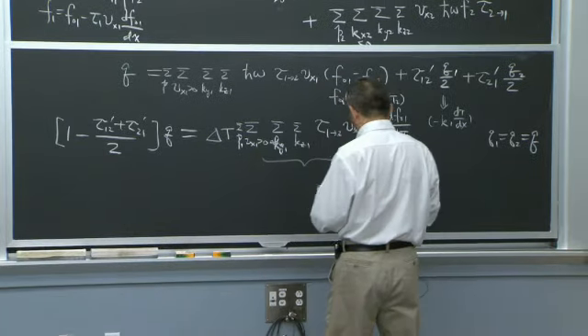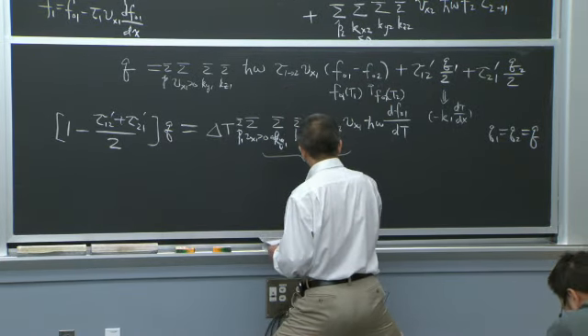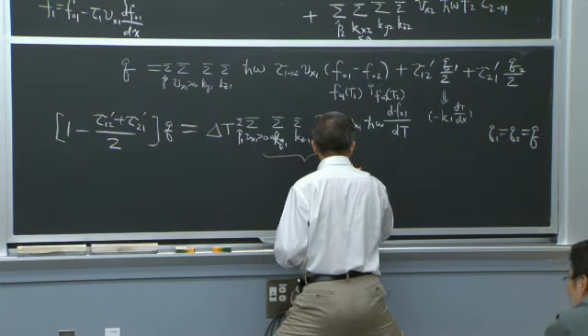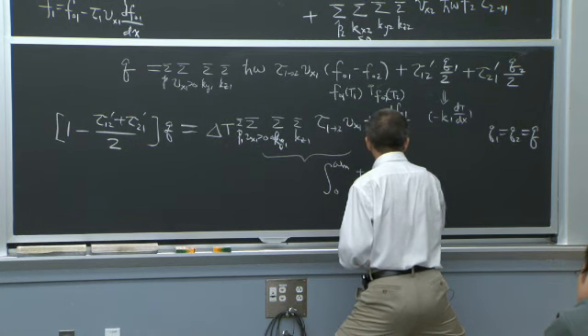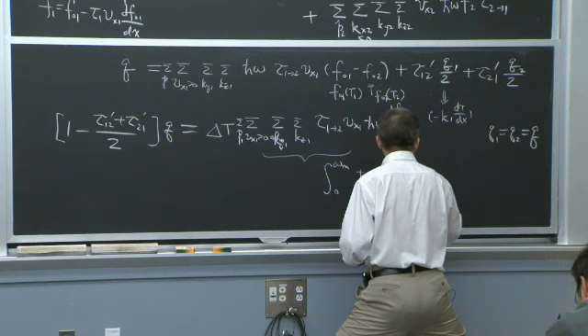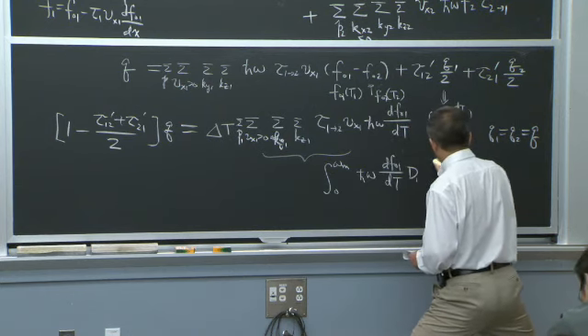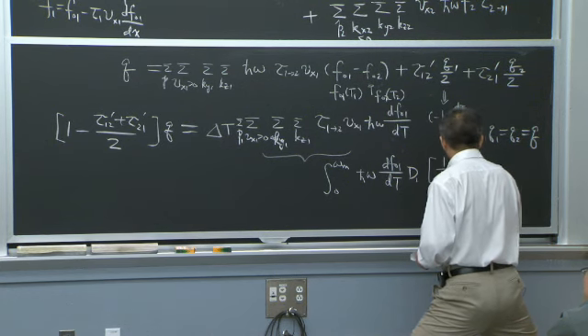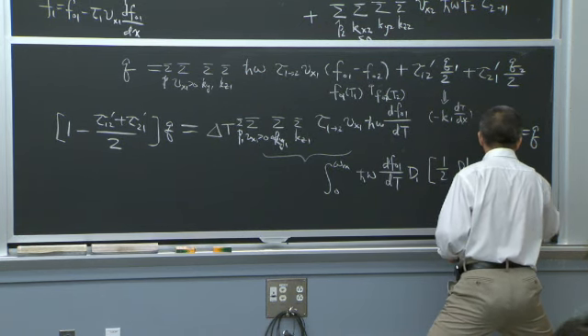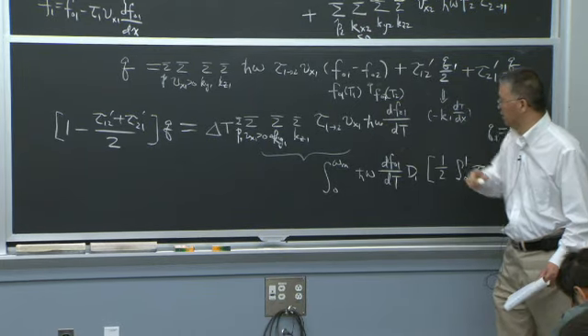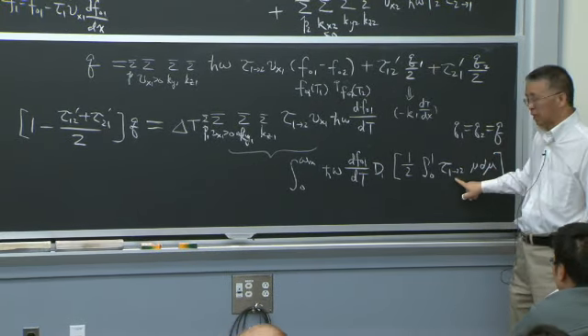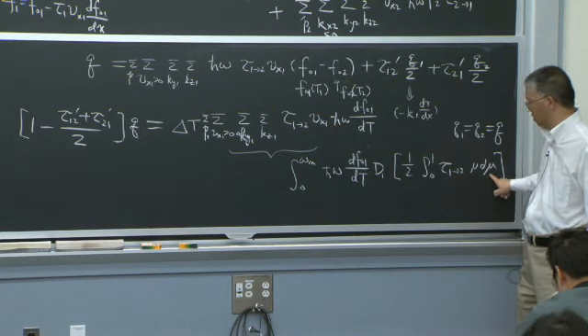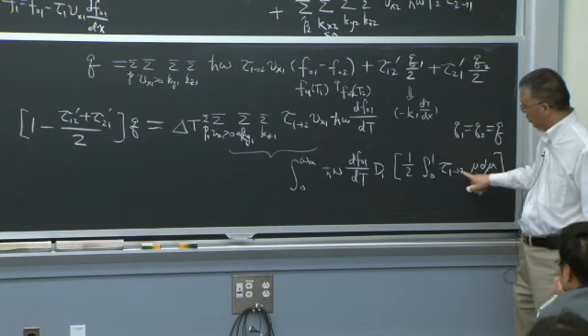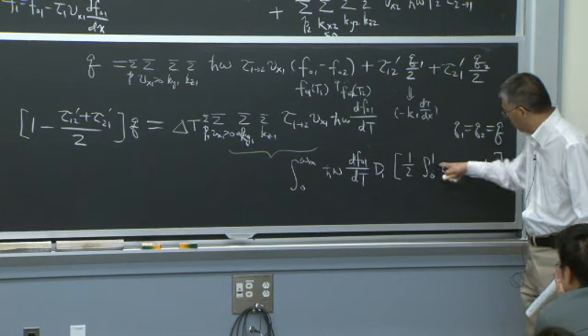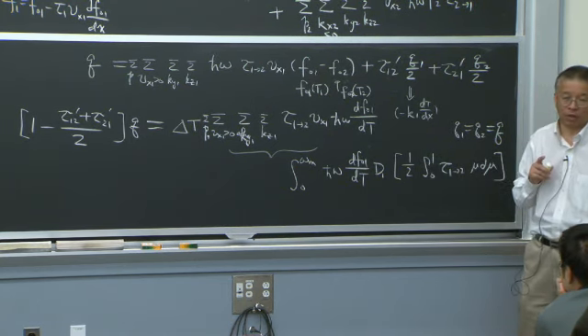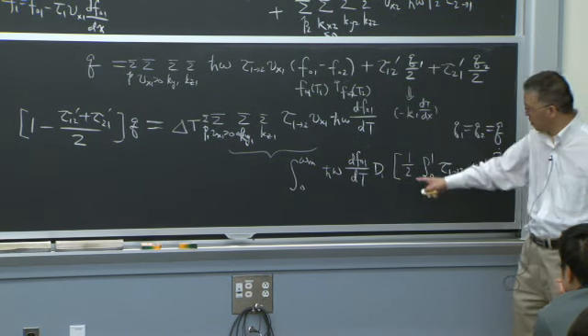So if you do this, you can write it as an integral from 0 to omega max of h bar omega dF01/dT and the density of states on the one side. And then on this side you have one half, integral 0 to 1 of tau 1 to 2 mu d mu. This comes from the sine, since VX1 has a sine theta. If transmittance is 1, this gives me one half mu d mu, right? So this is really one fourth. Two times this gives me the average transmittance weighted over sine theta VX1, so this should give me 1/4.